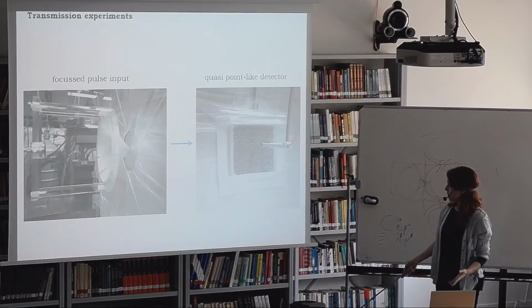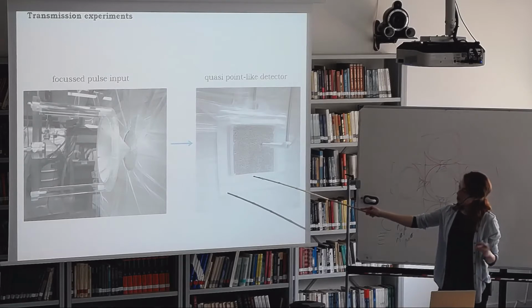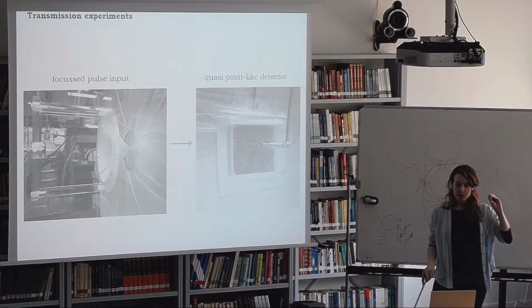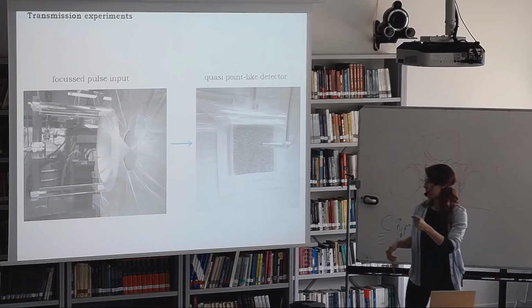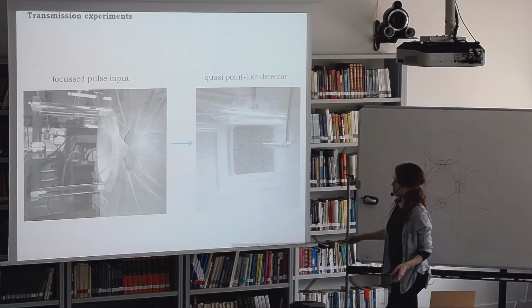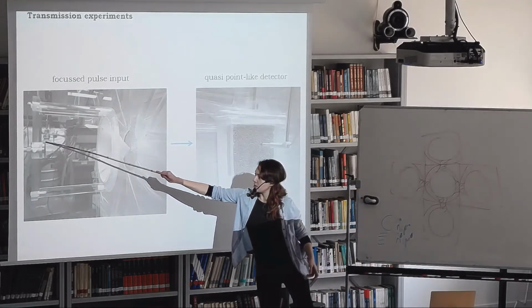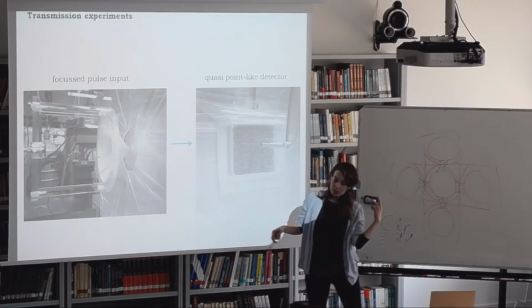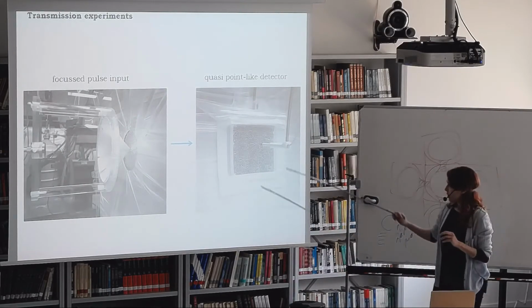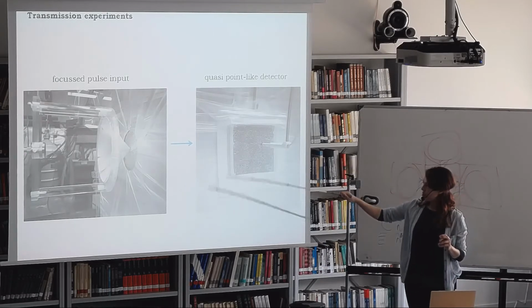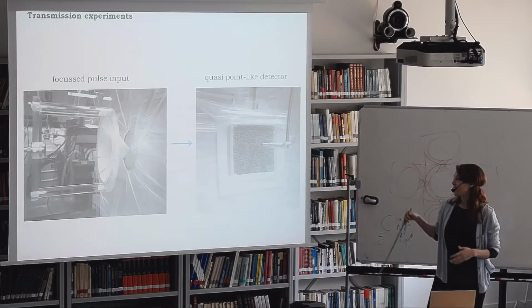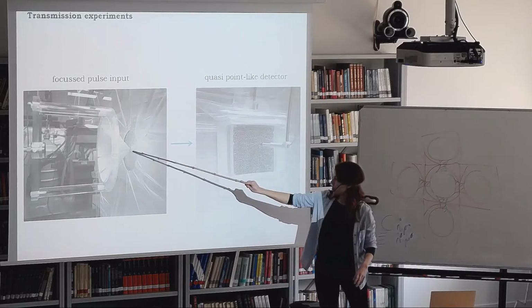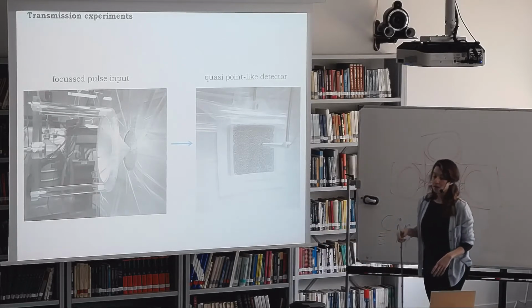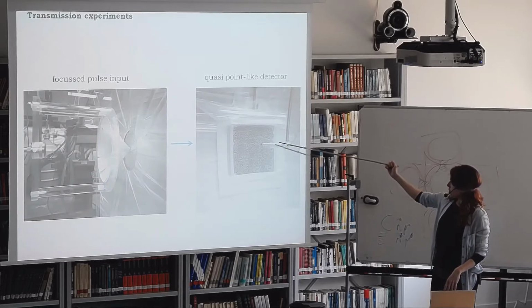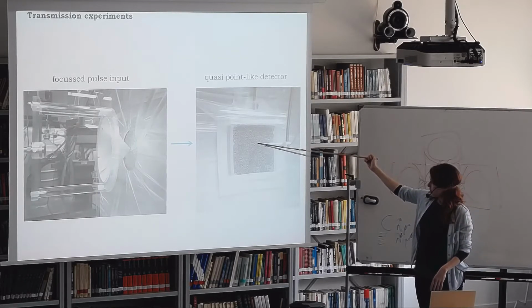So here are some pictures of the actual setup. In emission, we want to input a pulse only at one specific spot at the sample surface. So we use a focused ultrasonic transducer. You can kind of see it here. So this sends a focused beam. And then to help the focused beam really only come in at one place, we use this sort of cone-shaped guide to really only make sure that we're inputting at this one spot. Then in detection, we have a small quasi-point-like detector that detects what comes out really close to the sample surface.